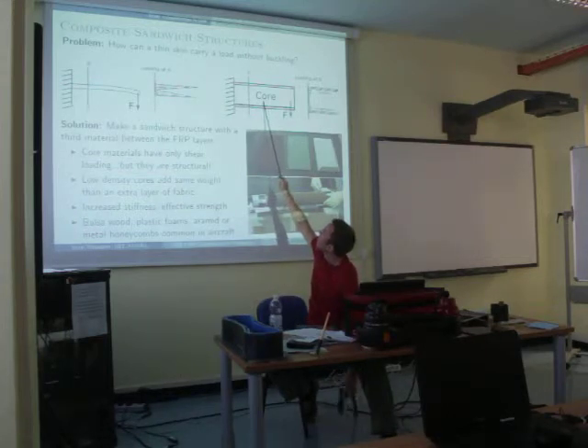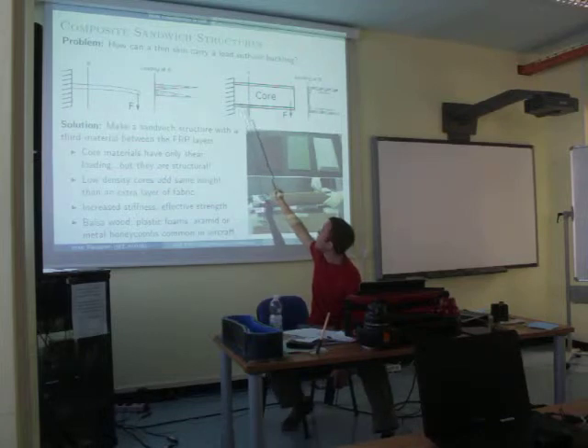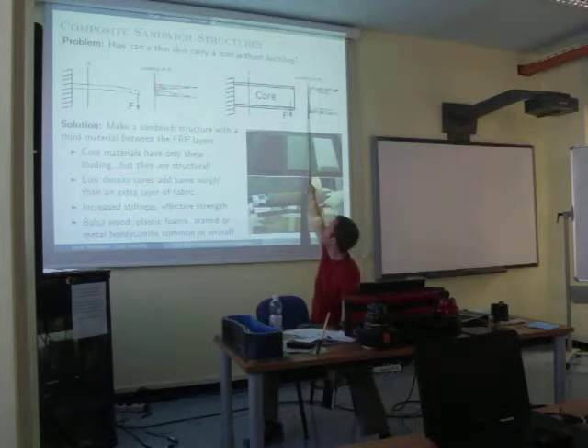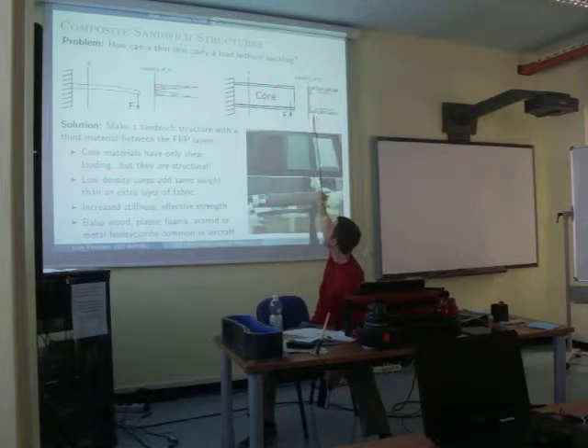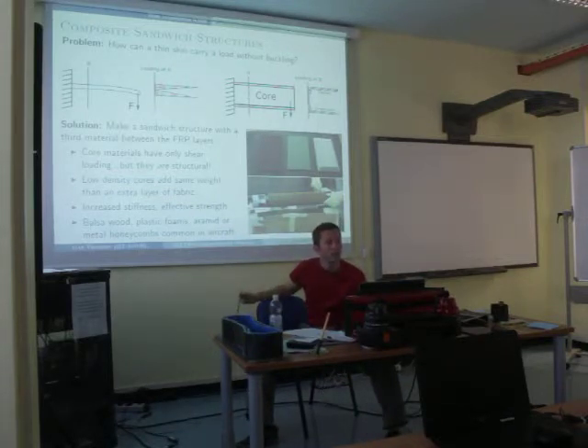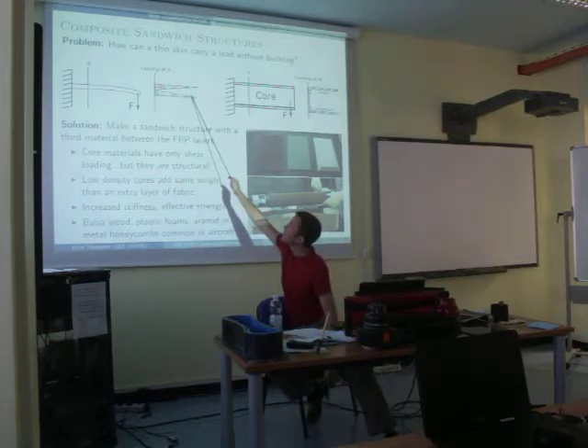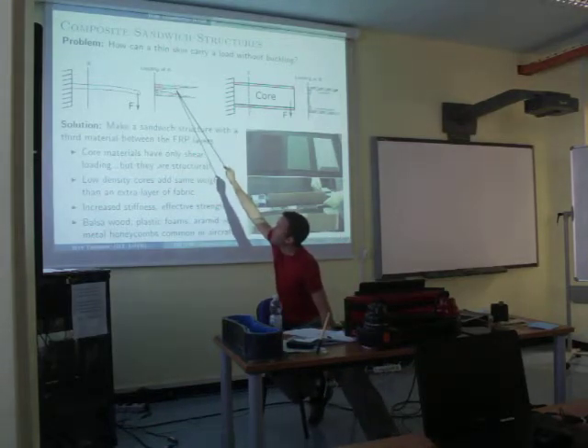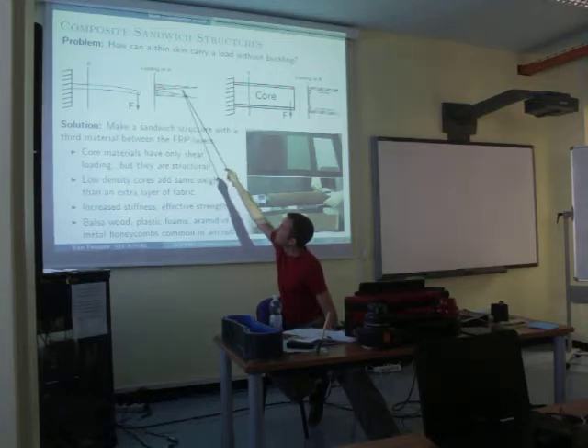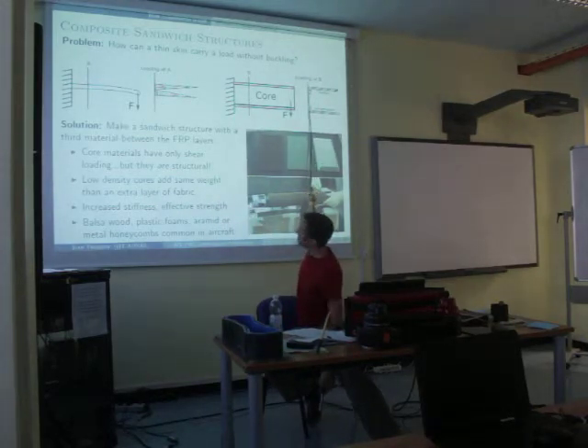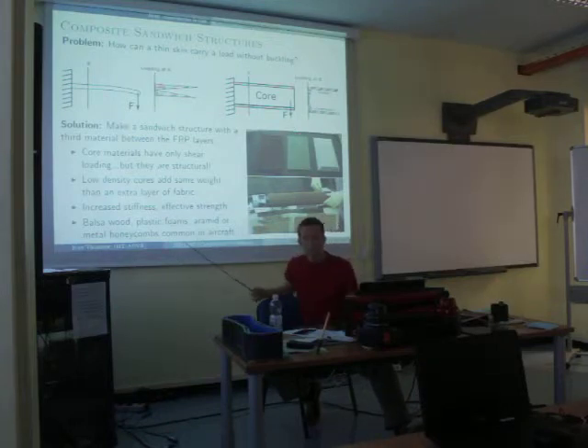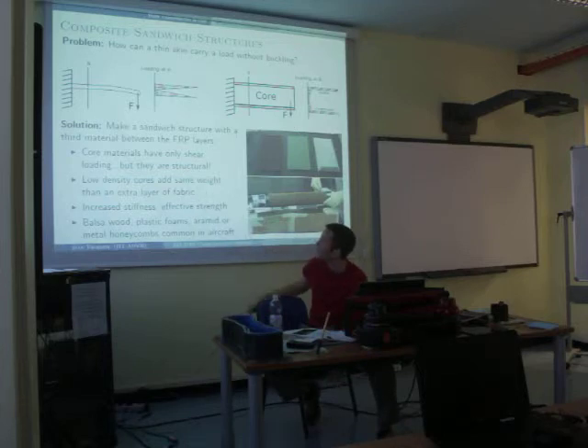If, however, we had a core, and the core has enough shear strength and compressive strength to keep the two surfaces apart, you end up with very little loading in the core because it's a little more flexible than the surface material, and you have all of the tension and compression loads in there. So you're using the fiber much more effectively. Instead of having just this heavier fiber in the center and just a little bit on the surfaces carrying things, you can more effectively use the carbon fiber material. So the core materials only have shear loading, but they are structural, as we'll see.